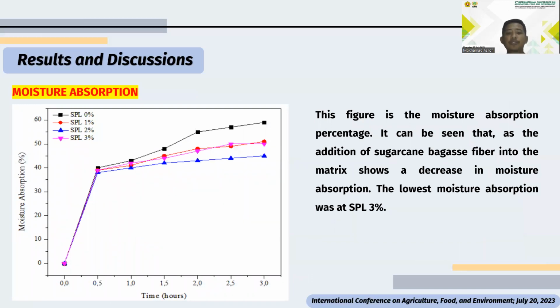The moisture absorption also supports the tensile and scanning electron microscope results. We know that this figure is the moisture absorption percentage. It can be seen that with the addition of sugarcane bagasse fiber into the matrix, there is a decrease in moisture absorption, and the lowest moisture absorption was in SPL 2%. This indicates that there is a correlation between tensile strength, moisture absorption, and fracture morphology. The best result is the addition of sugarcane bagasse fiber 2% in the matrix of cassava starch and lecithin.